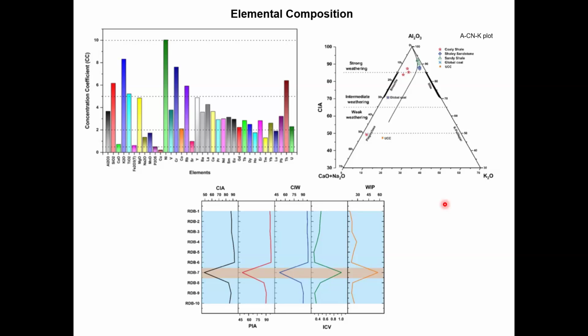We plotted these diagrams, which again suggest that these samples plot in a strong weathering zone. That means that during the formation of these samples there was strong weathering, suggesting warm and humid climatic conditions during the formation of these deposits. Again, these ratios were plotted, and you can see that most of the samples suggest formation in a warm and humid climatic condition, but one particular sample, RDB7, is totally different from the other samples, suggesting a variation during the deposition.